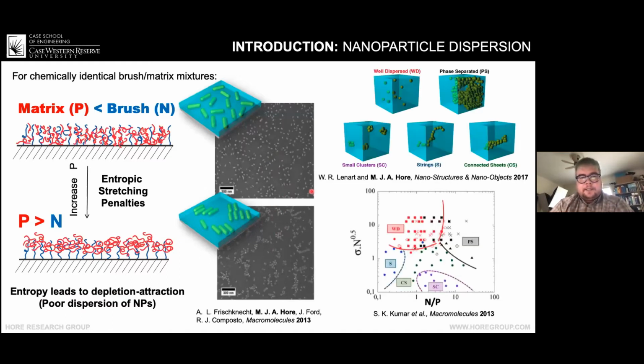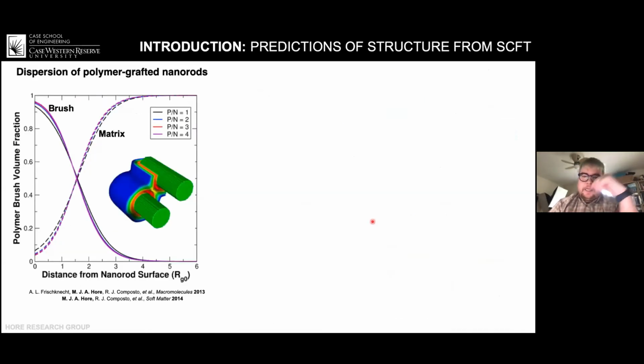And so it's simply this autophobic dewetting, this process that's entropic in nature, that gives rise to the myriad structures that we see for nanoparticles in these materials. By now we've mapped out phase maps for spherical particles and rod-like particles, so we have a pretty good understanding of the physics behind this. What was puzzling, though, is that you can perform self-consistent field theory calculations to calculate the density of the brush away from the nanoparticle surface and correspondingly the density of the matrix. And although you see these huge effects in terms of the dispersion of the nanoparticles, you don't really see an appreciable difference in the density of the brush.